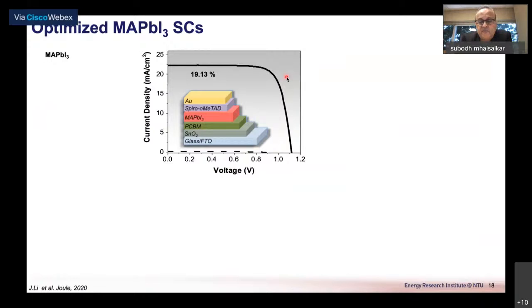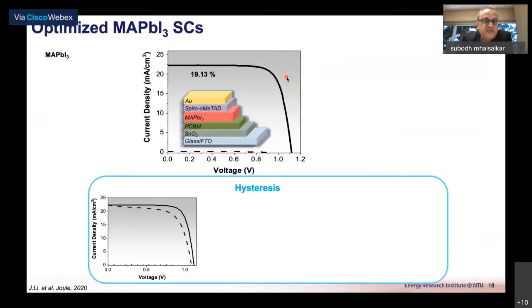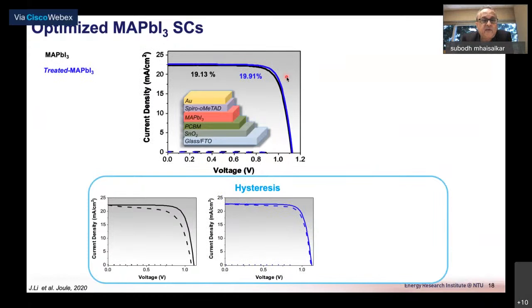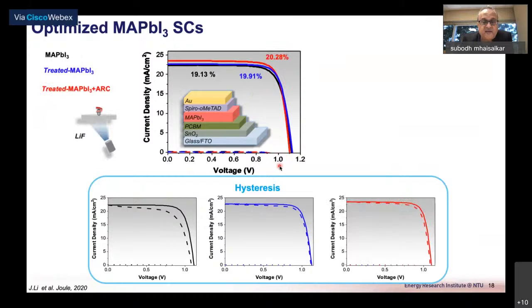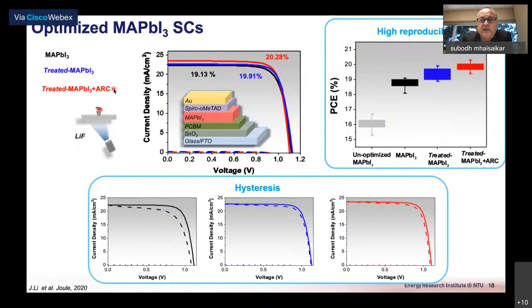So the as-deposited methyl ammonium lead iodide gave us about 19.13% and a certain level of hysteresis. As we do the treatment of these materials, you could see that the hysteresis was suppressed, and more or less the VOC as well as the JSC did not change a whole lot. One of the factors that did affect is the fill factor. Further deposition of lithium fluoride to form the anti-reflection coating really gave us efficiencies in excess of 20.28%.